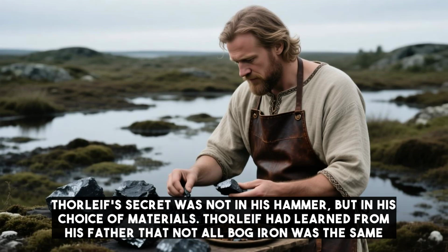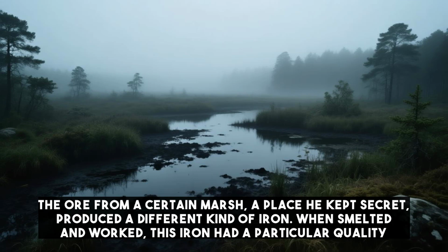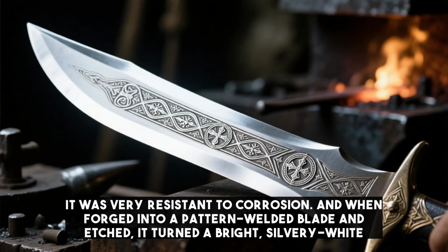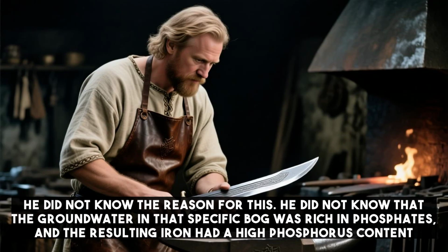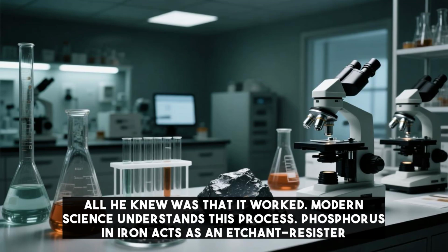Thorleif had learned from his father that not all bog iron was the same. The ore from a certain marsh, a place he kept secret, produced a different kind of iron. When smelted and worked, this iron had a particular quality. It was very resistant to corrosion, and when forged into a pattern-welded blade and etched, it turned a bright, silvery white. He did not know the reason for this. He did not know that the groundwater in that specific bog was rich in phosphates, and the resulting iron had a high phosphorus content. All he knew was that it worked.